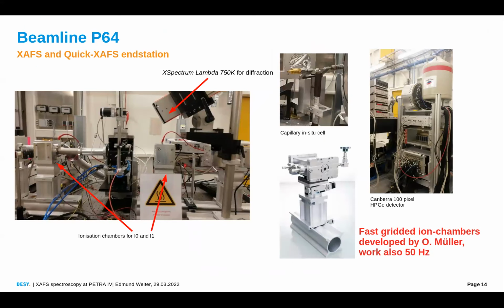Good, some pictures from P64. This is the standard setup with the ionization chambers here and there, with the sample between the two ionization chambers. Here is the Lambda detector installed, a 2D Lambda detector, to measure the diffraction pattern from the samples. And the in situ cell, sorry, a 100-pixel germanium detector, which is not very popular among the users and among the beamline scientists, because it's a bit tricky to use, let's say. It's actually easier to use a 4-pixel SDD detector and achieve even higher integral count rates with these 4 SDDs than with this meanwhile rather old 100-pixel germanium detector.